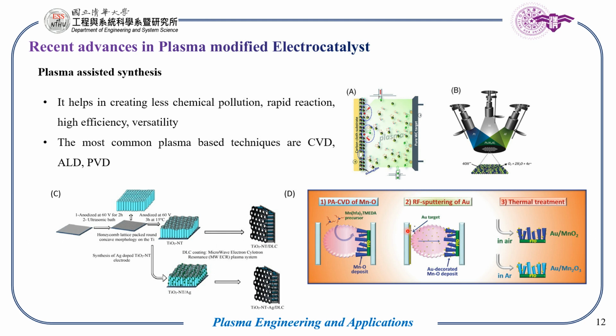And figure D shows manganese oxide, a metal oxide, which was grown on a conductive glass, and this was done by plasma-assisted CVD, that is plasma-assisted chemical vapor deposition. And subsequently the Au, that is gold nanoparticles, was used to functionalize these conducting wafers, and they further used it for HER generation.